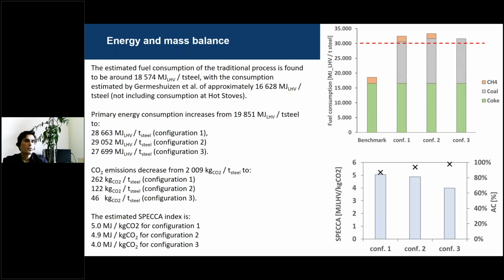presentation. With regard to the SPECCA index, which is the specific primary energy consumption for carbon avoided, this decreases with the increase of efficiency level from configuration 1 to configuration 3, where in the last configuration we are able to recover not only the blast furnace gas and the basic oxygen furnace gas, but also the spent solid coming from calcium looping. So a complete integration between calcium looping and steel industry reflects in a lower SPECCA, and this means a more efficient